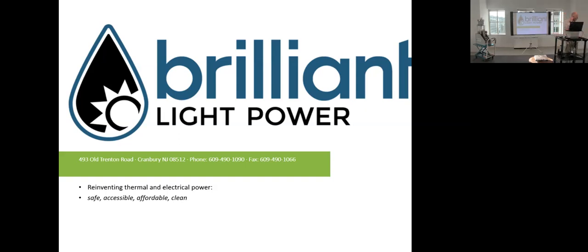Yeah, well, there's a very, very small amount of oxygen that's flowing through the system. It's actually on the order of only 1 or 2 SCCM. So that's really limiting the heat of reaction in that oxygen and hydrogen reaction. Turns out if you do that simple calculation, the enthalpy of that reaction for the entire 5-minute calorimetric test is about 100 joules of energy released from that reaction. So you're comparing 100 joules of energy to 25,000 kilojoules. That's 6 orders of magnitude difference. So it doesn't substantially enter into the calorimetric result.